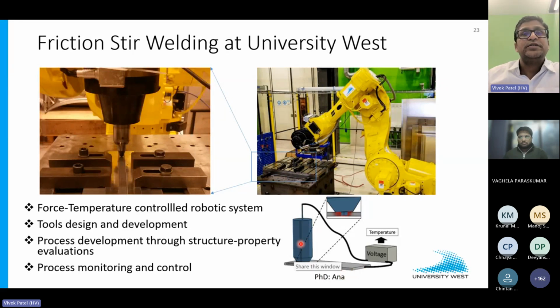So when the tool makes contact, the circuit is complete, and we measure the voltage. That voltage changes when the temperature changes, and this temperature change depends on the type of material of the tool and the workpiece. That voltage difference at different temperatures we calibrate as the welding temperature. So if we set the temperature for a particular aluminum at 500 degrees Celsius, then we will ensure that the welding has been done at 500 degrees Celsius, irrespective of the heat sink, irrespective of the heat geometry.